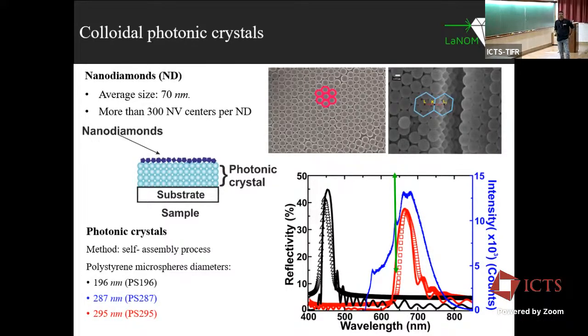So we call it a band gap. We started this work around 2016-17. At that time we brought nanodiamond, which was an ensemble of NV centers from Sigma-Aldrich, and we drop-casted it on top of photonic crystals. We wanted to see whether this photonic crystal, this colloidal-based low index system, can change the emission properties